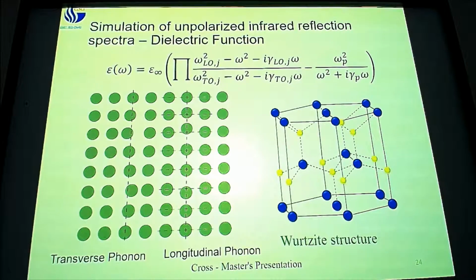And all of this, although it's nicely laid out in a 2D grid, is actually happening in my Wurtzite structure model. So we have atoms that are moving up and down like this, and atoms that are moving in and out like that within my Wurtzite structure. Those are the phonon frequencies that I'm talking about. The gamma functions here are the damping coefficients for those phonon frequencies, and this is the damping for the plasma frequency. The plasma frequency comes out of the free charges that are able to move around within my structure. So I have electrons or holes that can move around, and that gives me the information about that.